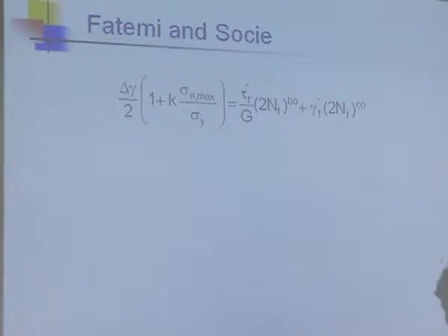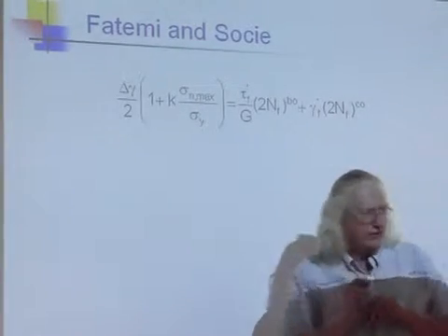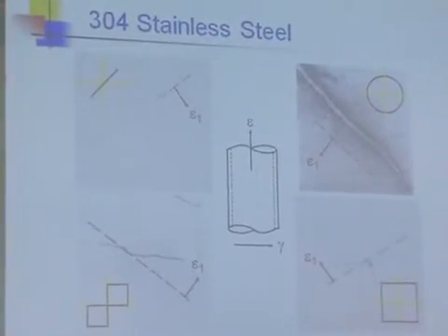They also convinced me. He said, "Oh, we need an adjustable constant here so we can make the curves look a little bit better." I always use a constant K of 0.3, and it works pretty good. So I never deal with calculating it. You can write it in terms of shear or tension. You got to be a little bit careful though in all of these.